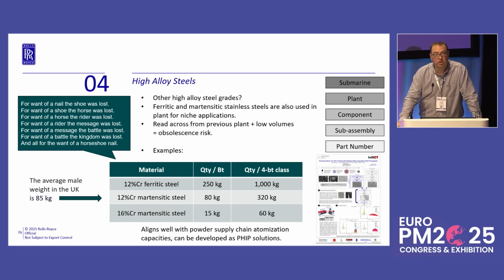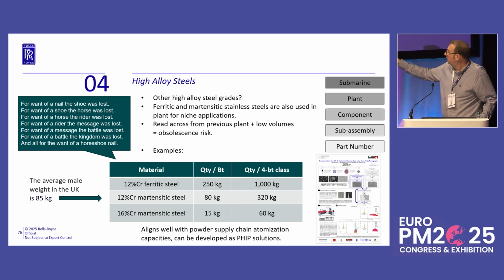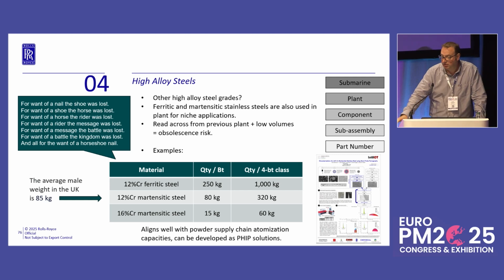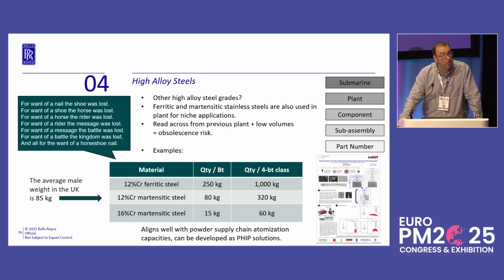So this is one of the things that we've been looking at. The post from the bottom right-hand corner is one of the things that we've tried to get a good handle on. Life is quite easy for us when we make our austenitic stainless steels, because we effectively make either 304 or 316L grade, and then we do nitrogen atomization, so we effectively get 304LN or 316LN for free. And they're well-established grades, and everyone understands what the nitrogen does.